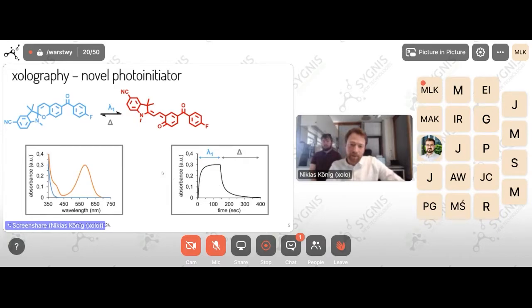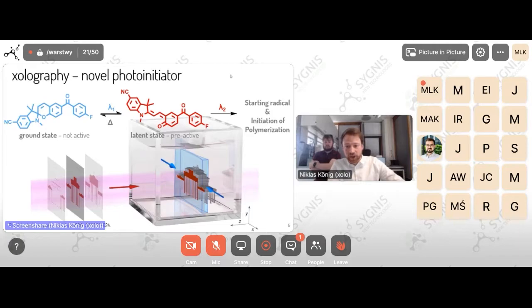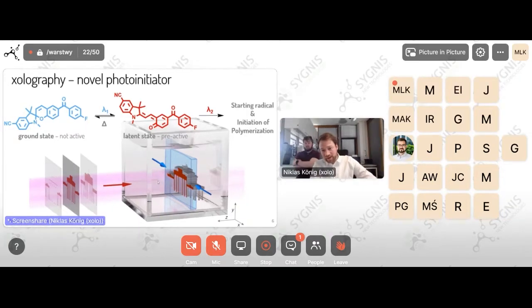And that's very important. So it is possible at a certain point in the volume to have this merocyanine form, and as soon as you switch off the light, it won't be there anymore. Because in the end, you make this benzophenone moiety photochromic, so it can change the absorption band. And this is what we use in our technology, as only this merocyanine open form can absorb visible light. We use this property to selectively address this molecule in the volume with visible light to induce the radical polymerization. So only the ground state of the molecule is everywhere in the cuvette, and only when we shine in light with the first wavelength, we have some of this merocyanine, and only at the intersection with the second wavelength, we activate the initiation of the polymerization.